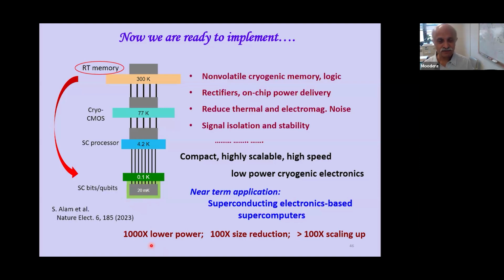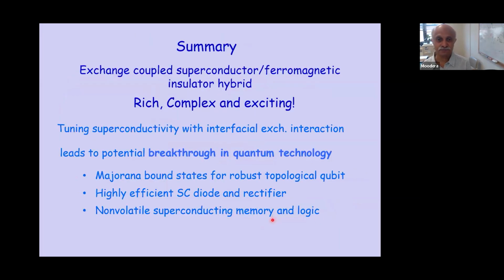Okay, so you can see that there is a 1,000 times lower power usage and a 100 times reduction in size, and it can be easily scaled up because our layers are just a double layer, triple layer, which can be produced at large wafer scale and can be patterned very easily. So we are able to already deliver. The near-term application is that you can use this for superconducting electronics-based supercomputers. That's the kind of program that's going on at Lincoln Lab.